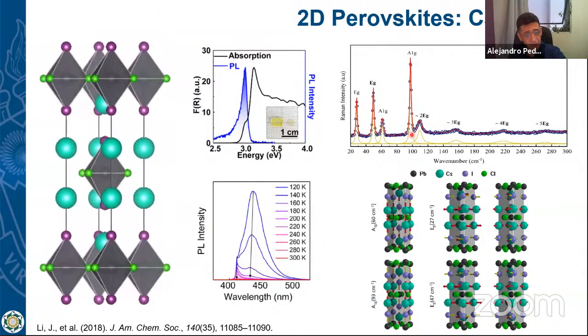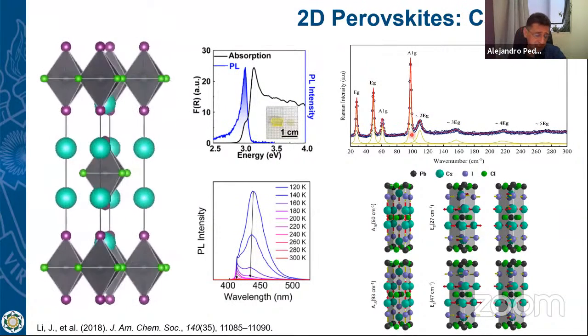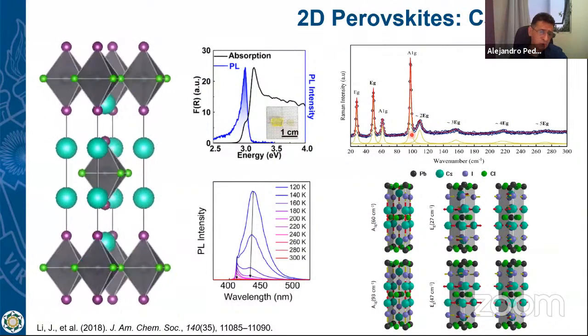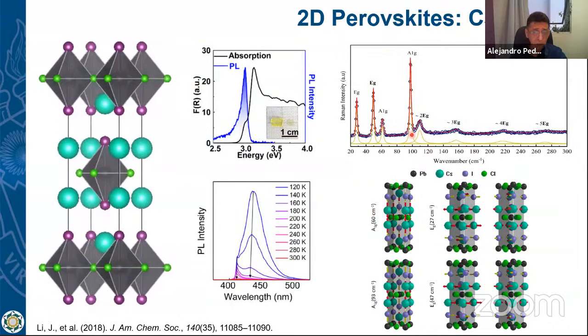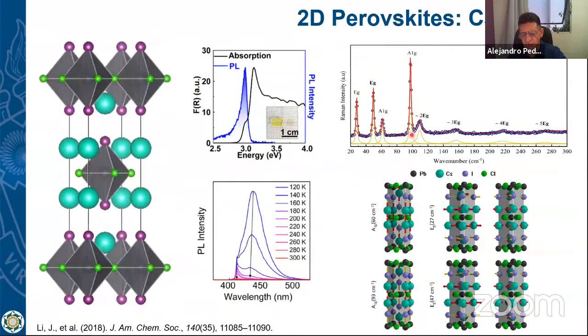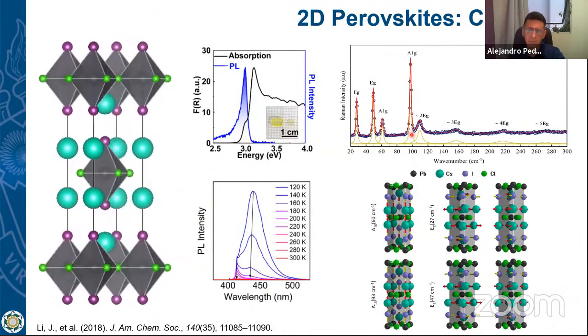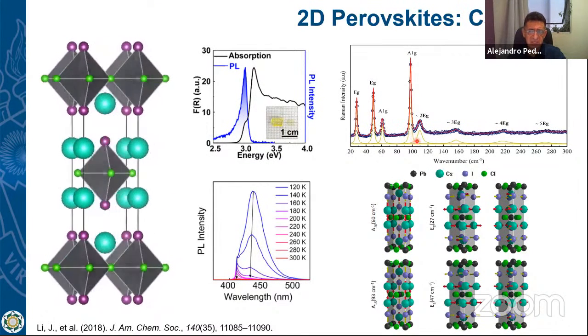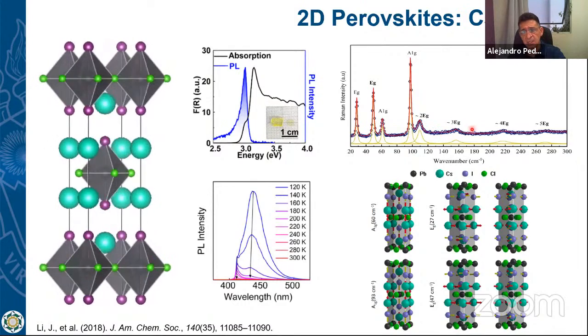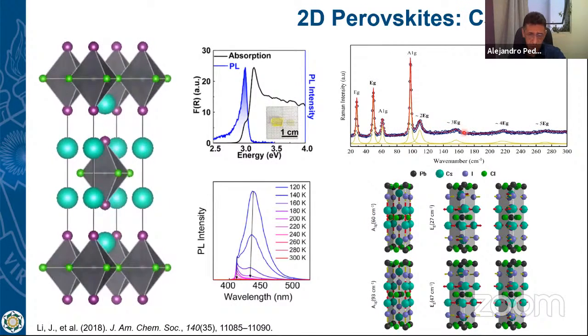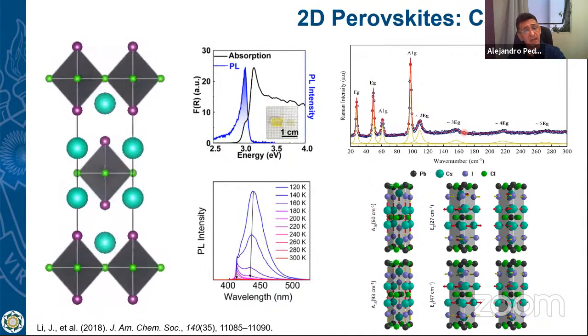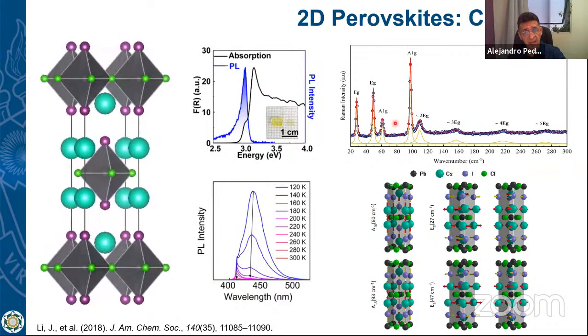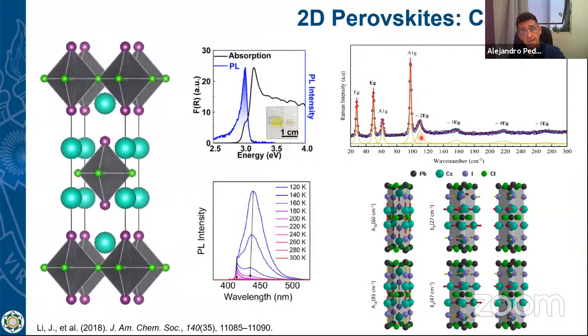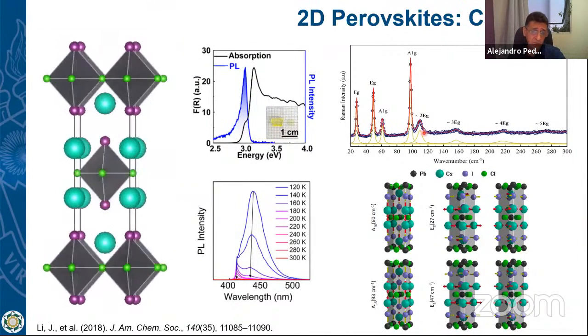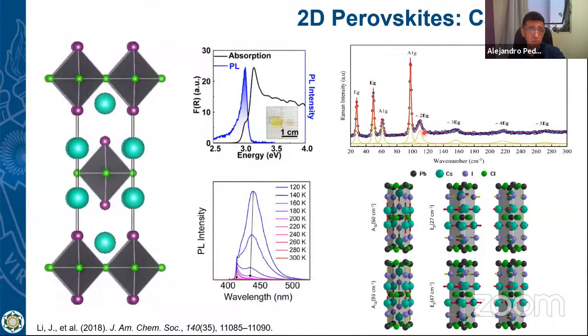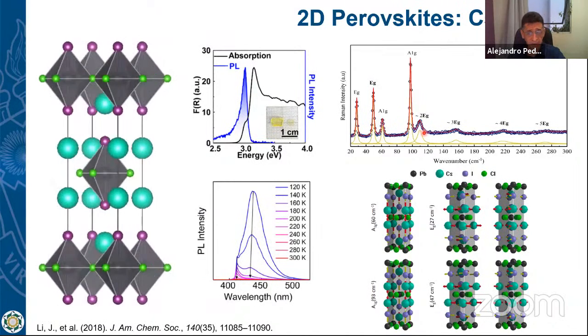In principle, if the crystal is purely harmonic, overtones are not allowed. It is due to the quantum selection rule of the transition of the harmonic oscillation. Maybe you studied something like that in the quantum mechanics course. But if there is something inducing some anharmonicity, you can see some overtones, which can be 2 times something, a combination of 2 modes, or they could also be vibrational modes which are just allowed by symmetry to be observed in the infrared, but due to this anharmonicity, you can observe them in the Raman spectra also.